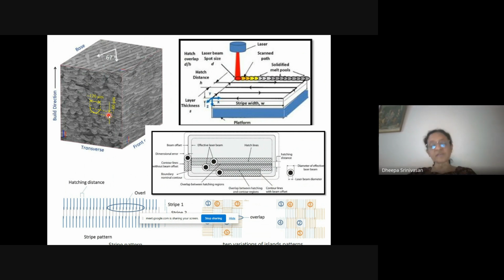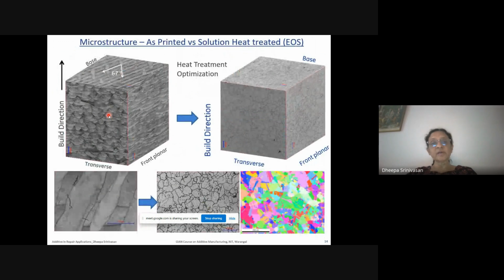But the application itself needed high temperature properties. I told you it was a hot section part, isn't it? So what we went on to do is, we took the microstructure of the as-built structure. I showed you these. We did some optical microscopy and very detailed scanning electron microscopy, as well as very detailed transmission electron microscopy, to make sure that we understood what was the phase and what were any metastable phases, so that the equilibrium stability could be mapped thoroughly from the as built structure.